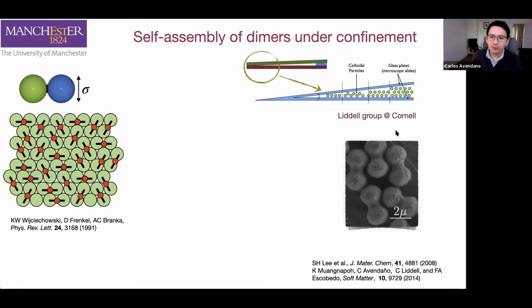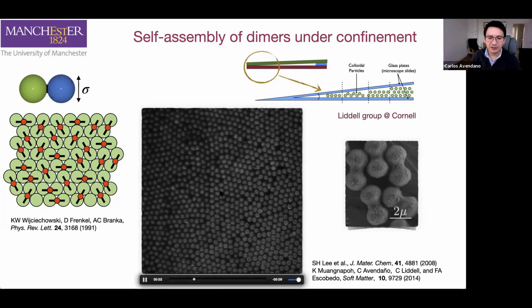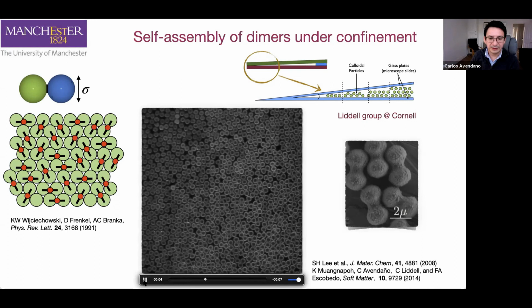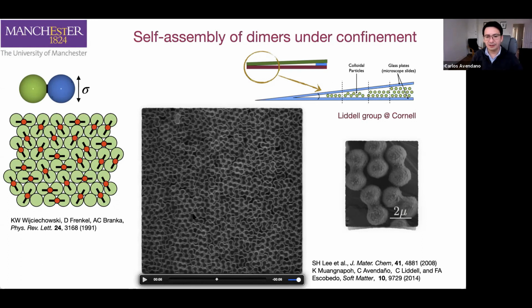Well, with a group of Liddell, we collaborated again, and she carried out the experiments for dimers. And using the same experimental technique of the wedge, she was able to observe the formation of these monolayers and bilayers. The monolayers will be the experimental counterpart from the simulations from Dan Frenkel. And we can observe that exactly the same that was reported in the simulations is what we observe in the